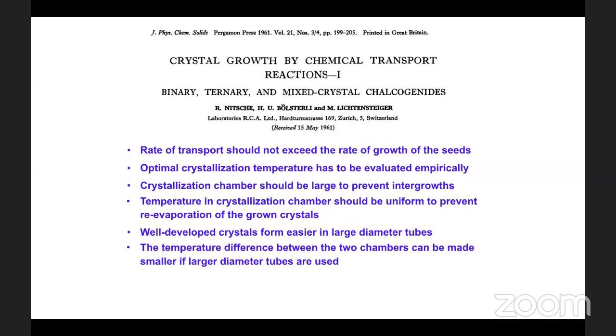There are many problems that occur while growing crystals, because the transport rate should not exceed the growth rate. If that happens, you won't get very nice crystals. Also you have to optimize the temperature evenly across the crucible. The crystal chamber should be very large to prevent intergrowth. In between, some intermediate compounds are also possible, so that's why you have to maintain a very large container. These are the parameters we have to optimize during the crystal growth.